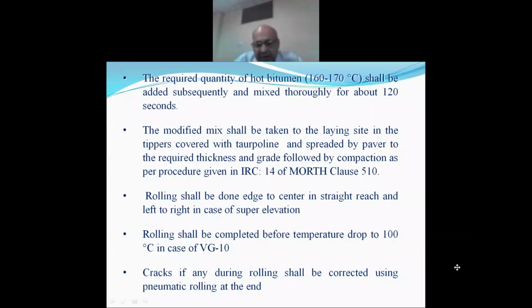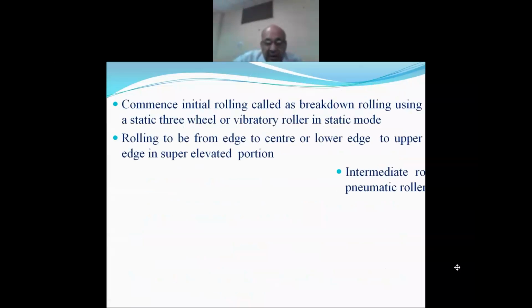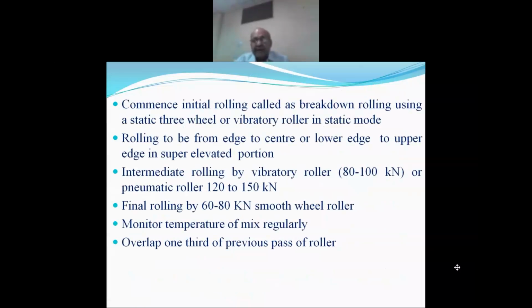Preparation and laying. Requisite quantity of the plastic waste, that is 0.88 kg per 10 square meter area, of required quality. Quality means it should be passing 4.75 mm sieve. Waste plastic powder should be passing 4.75 mm sieve and retained over 1.18 mm sieve. It shall be added to the mixed aggregate heated to about 150 degrees centigrade before addition of the bitumen, 14 degrees higher. Base plastic aggregate shall be mixed thoroughly for 30 to 60 seconds.